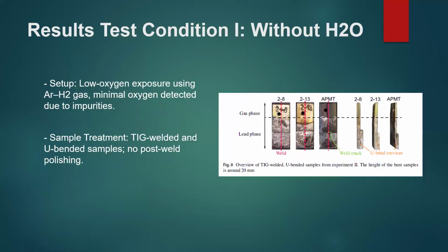For the result without H2O, the setup used low oxygen pressure with argon hydrogen gas, with minimal oxygen detected due to impurities. Sample treatment showed TIG welded and U-bend samples were not post-weld polished.